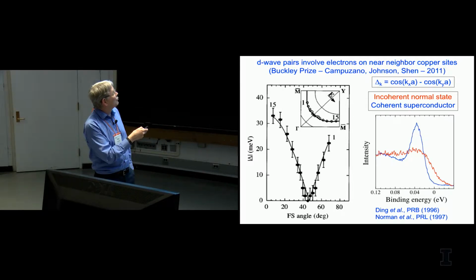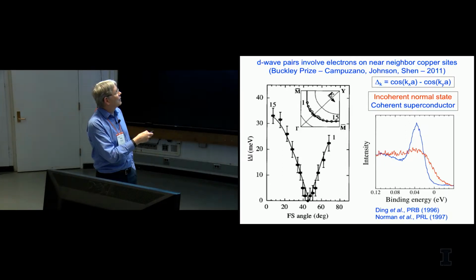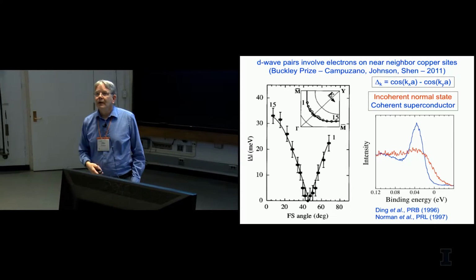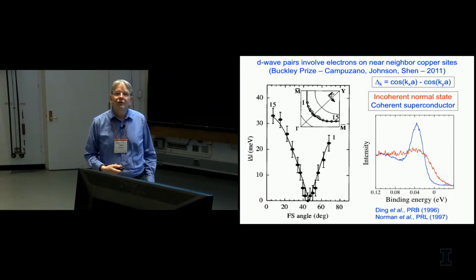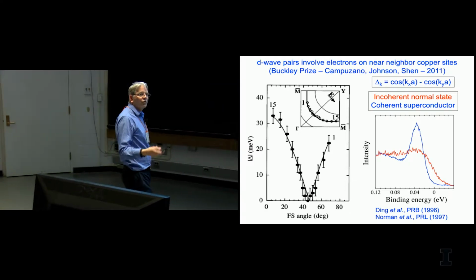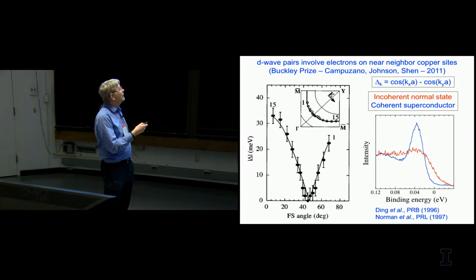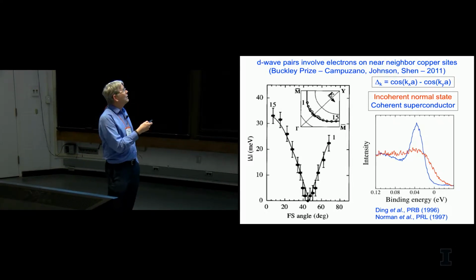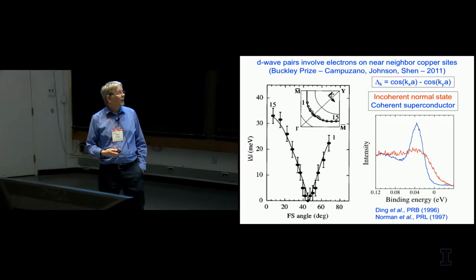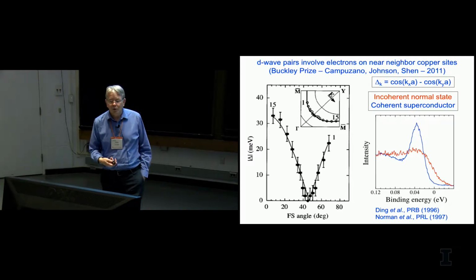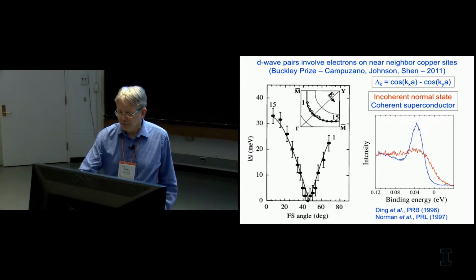And important fact number two is if you look at the normal state, say out in the antinodal region where the superconducting gap is largest, the normal state for most of the phase diagram is incoherent, but in the superconducting state you get coherence. And this is again a big difference from BCS theory where you go from a coherent normal state to a coherent superconducting state. Here over most of the phase diagram you go from an incoherent normal state to a coherent superconducting state.